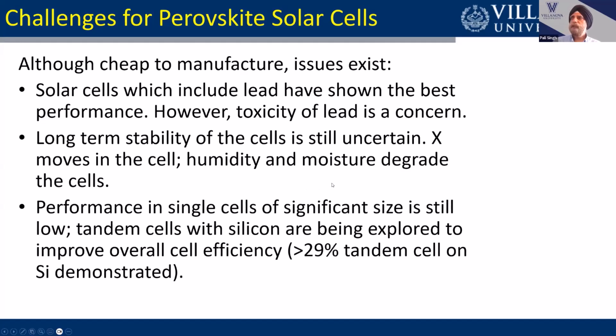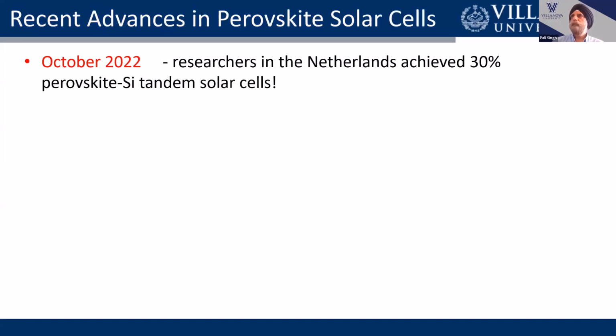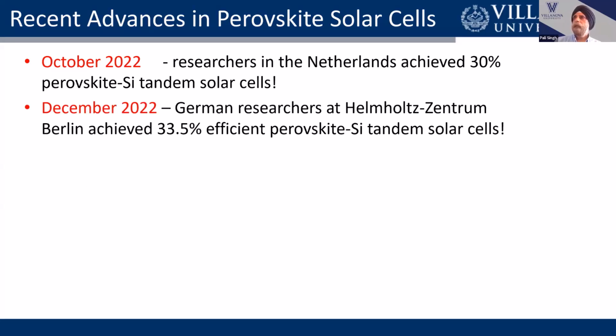The humidity and moisture degrade the cells over time. And performance in single cells of significant size is still low, but tandem cells with silicon are being explored, and they've demonstrated over 29% efficiency when we have a silicon base cell. So just to show you some of the more recent advances in perovskite solar cells. So in October 2022, researchers in the Netherlands achieved a 30% perovskite silicon tandem solar cell.